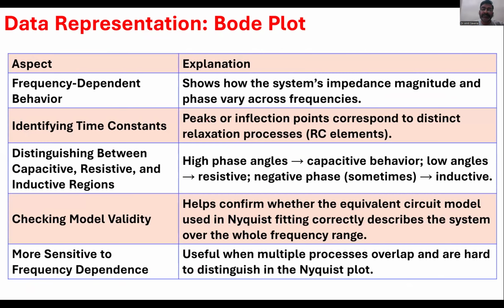Identifying the time constants, the peaks or the inflection points corresponding to distinct relaxation processes, is known as an RC element. This distinguishes between the capacitive and resistive regions. High phase angle is the capacitive behavior, low phase angle is the resistive behavior, and negative phase angle is the inductive behavior. So by the Bode plot, you can analyze what sort of behavior is shown by your sample when it has been placed between two electrodes, right?